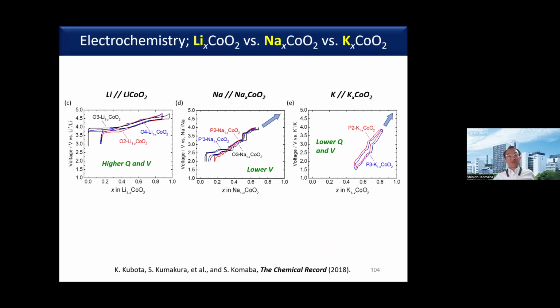So how about cobalt for lithium, sodium, and potassium? The lithium case shows higher reversible capacity and also moderately high voltages, which is compatible with carbonate ester-based organic solution. In the case of sodium, the reversible potential is lower, and potassium is much more sloping with limited capacity. But please note that if we extract all of the lithium, sodium, and potassium, finally we will have cobalt dioxide, which is free from alkali metals. Then for CoO2, all of them show around 5 volts because of the same electronic condition after fully extracting lithium, sodium, and potassium.